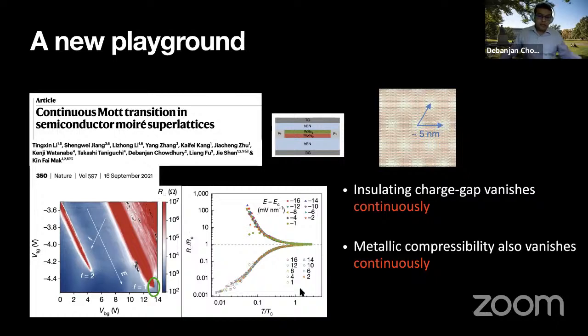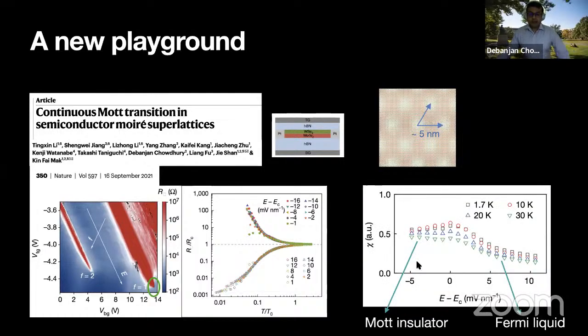I should have also said that there is no sign of hysteresis in this system. So it really does look like a continuous transition. You can also measure the compressibility that also vanishes continuously as you approach the transition from the metallic side, okay? Now this is all good, but one of the most interesting things about the system is that you can measure the spin susceptibility across this transition. And what you find is that basically as you go through the transition from your Fermi liquid metal to the Mott insulator, the spin susceptibility evolves rather smoothly.